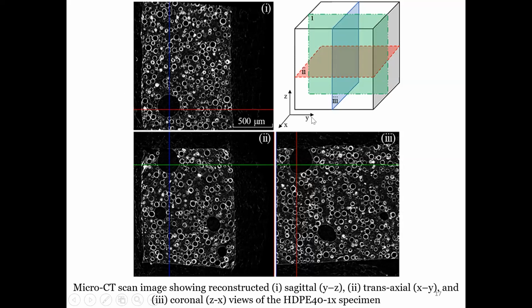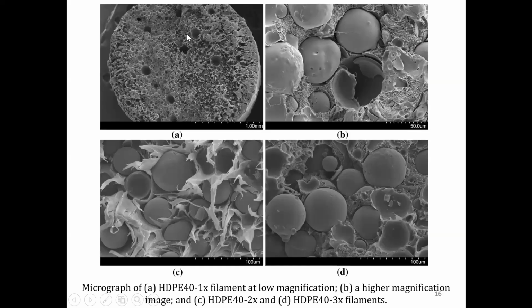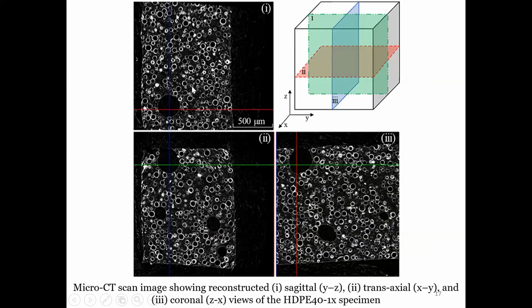So this is a micro CT. You can see 1, 2, 3 planes here. Across plane 1, this is how the micro CT looks. This is how the micro CT looks across plane 2, and this is plane 3 here. Again, micro CT shows you the dispersion, and you can see large voids here. You can very well correlate these large voids with whatever is shown in A. Those are being seen here.